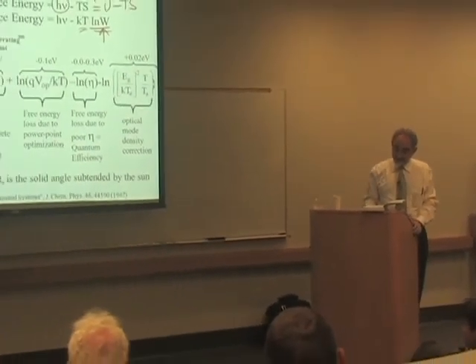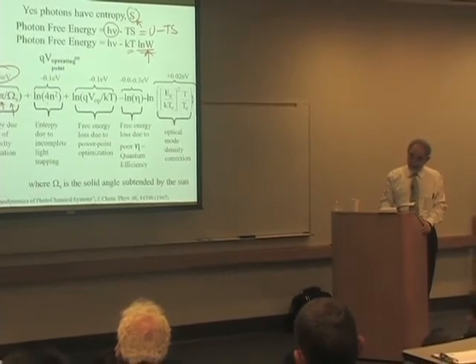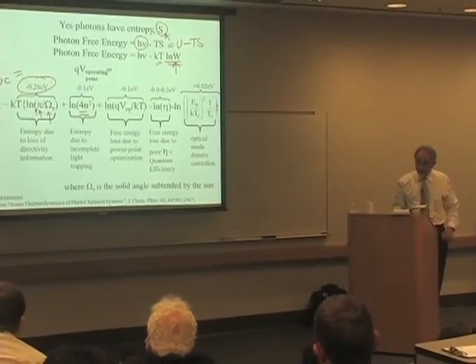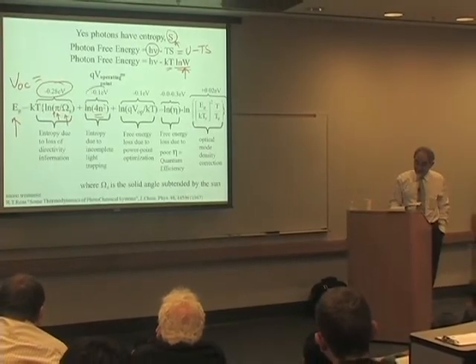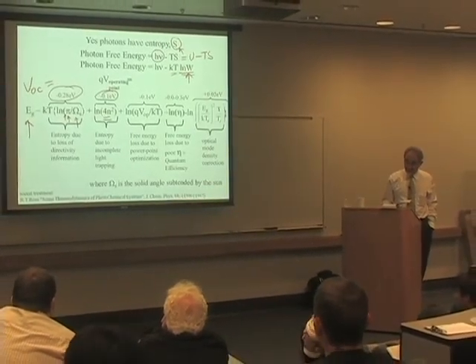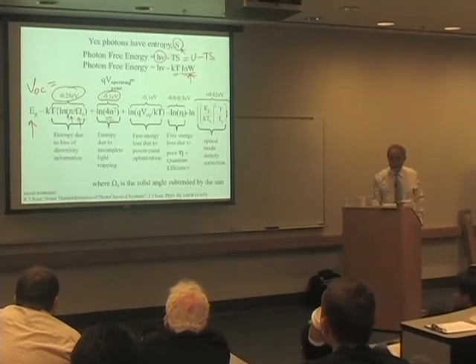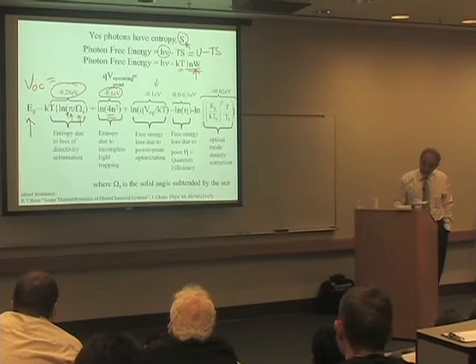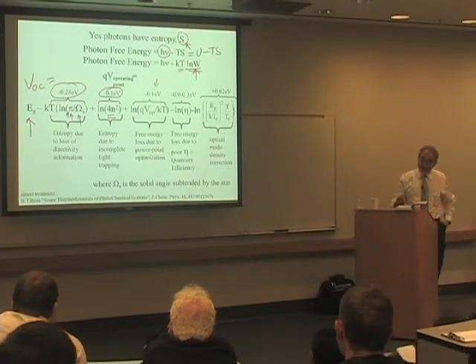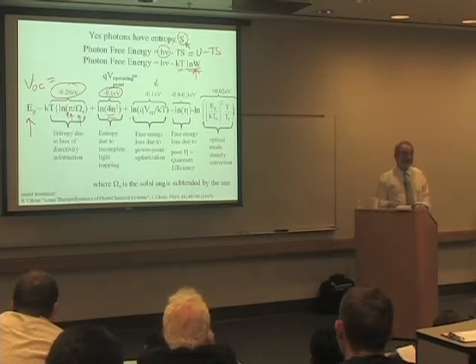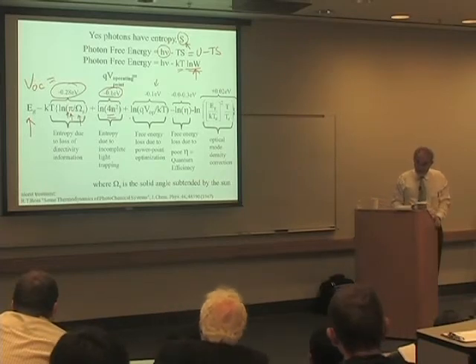Let me go on to the other entropy terms. I talked a lot about 4n squared. Now, suppose you take no advantage and you're totally ignorant of this 4n squared. That represents an even smaller internal angle, because when the sun refracts on the way into the semiconductor, that solid angle is even smaller. So either you take advantage of that with light trapping or you don't. If you fail to do the light trapping, you lose a tenth of a volt. That was the kT log of 4n squared term. So there's another tenth of a volt you give up, okay? Now, then there's another tenth of a volt. It's the one where you have to give the electrons and holes a reason to go into the wires rather than simply staying inside the semiconductor. So that reason, I went over it with you.